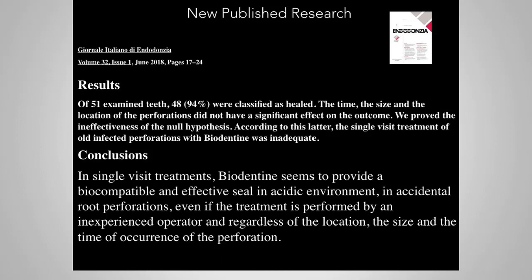So the outcome really was that in single visits, Biodentine provided a biocompatible and effective seal in an acidic environment for root perforations, even if the treatment was performed by an inexperienced operator and regardless of the location, the size, and the time of occurrence of the perforation. So, you know, is this a miracle material? There are no miracle materials.